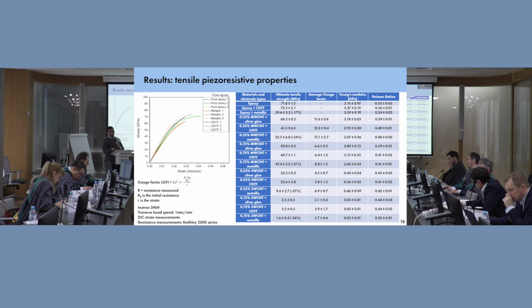We checked our UTS values, we checked our Young's modulus, we checked our Poisson's ratio, and we did the last two with the help of DIC. For the ultimate tensile strength, which is before plastic failure, we see that the metallic electrodes start to cause a significant loss in mechanical properties. And it's about 17% lower for this.